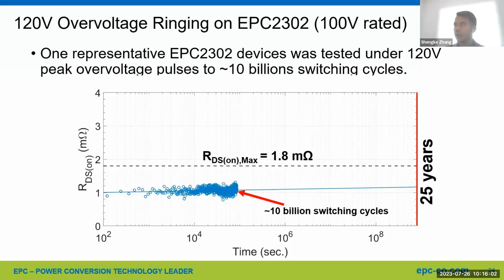Now let's test our latest PQFN device, EPC2302. So we showed 1 representative EPC2302 device, also 100-volt rated, to a whopping 10 billion cycles of 120 volt over voltage spikes, where very small RDS(on) shift was measured. So as you can see, the additional 8.5 billion switching cycles still follow the linear projected line, which provides further validation to the hot carrier trapping lifetime model we developed. It also shows very small RDS(on) shift over 25 years of continuous operation under repetitive over voltage switching. So the collective results demonstrate the extreme robustness of our 100-volt GaN FETs under 120-volt over voltage repetitive switching.